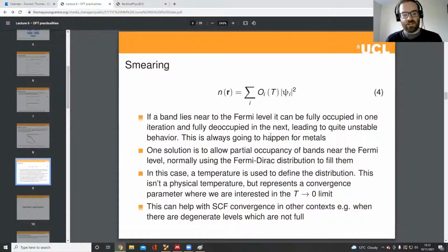If you want to do DFT properly for temperature, you need to also allow movement of the atoms. In this situation, we're just treating the temperature of the electrons, but we're keeping the atoms at 0 Kelvin. To do DFT properly with temperature, it's important to allow thermal energy to be placed in the atoms as well, rather than just the electrons. But when you're using this smearing trick, then you can take the energy as the smearing temperature tends to 0, and that's the answer that we're looking for.